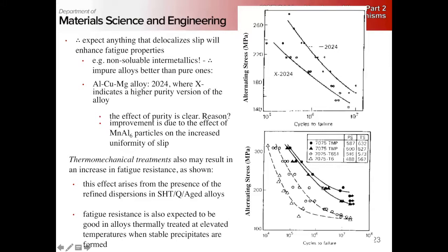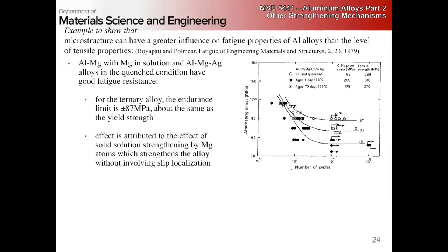So if we thermally treated, what's going on during this thermomechanical processing? Well, we're introducing a whole bunch of dislocations, and then heating it up, and so that's going to encourage the heterogeneous nucleation of secondary phase particles and cause the current particles to grow by coarsening.